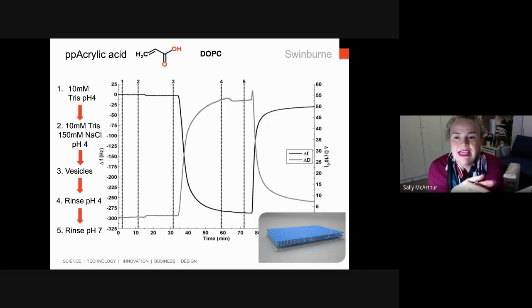So the vesicle now has actually opened up with that pH change. That rinse at pH 7 has basically driven an osmotic change. Some of the vesicles have come off the surface, and there's no longer vesicles sitting on the surface because the surface has become more rigid in the dissipation component, but there's still mass on that surface, and that mass is associated with a layer of collapsed lipid bilayer on that surface. So what this showed us was that we could use different surface chemistries and use pH to drive vesicle collapse, but the pH was actually an important factor.